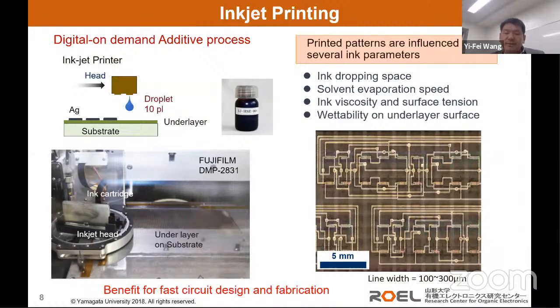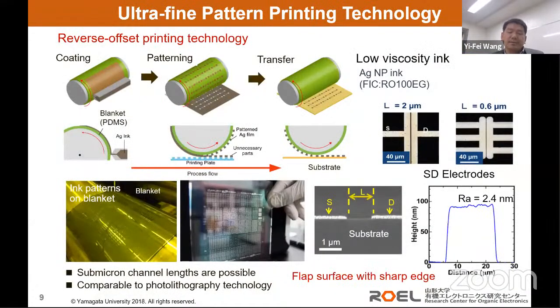And in here, we also show a figure of the circuit we developed by using inkjet printing on the flexible substrate. And actually, by adjusting the printing parameters, we can very easily fabricate the OTFT array with the channel length as short as 10 micrometer. And if we need higher resolution, we also can use another printing technology, the reverse offset printing.